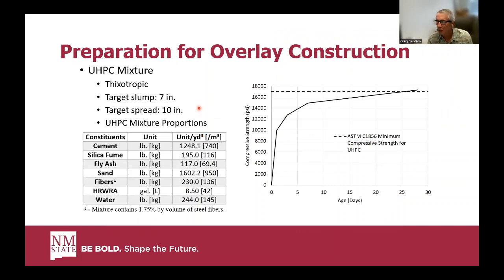So for the UHPC mixture, we submitted a mixture to NMDOT for the project. The key point here was that we wanted a mixture that was thixotropic. There were some slopes on this bridge that were 7%. And when you put the UHPC down on that surface, you don't want it to run by itself. You don't want a self-consolidating concrete type mixture, but you do want it to flow once you provide some excitation. So it should be stiff enough to hold its form until you hit it with a vibrator. And it's basically, as soon as you touch it with the vibrator, it should flow readily.